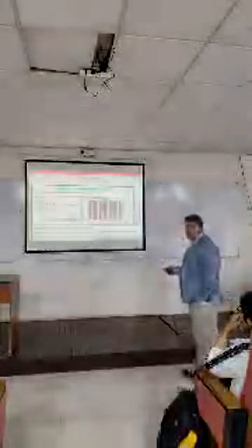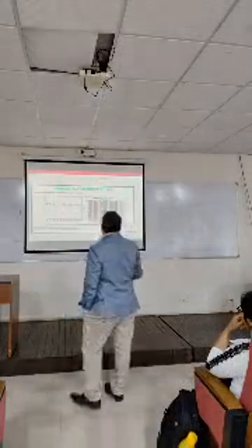Due to the formation of a covalent bond, this electrode surface shows a shelf life of up to 63 days. The first one was 35 days, and due to the covalent bond we observed that our shelf life increased up to 63 days. We have also checked our developed sensor on liver cancer patient samples, and it is again acceptable. The error percentage is only about 2%. In the previous one, it was about 5.8%.